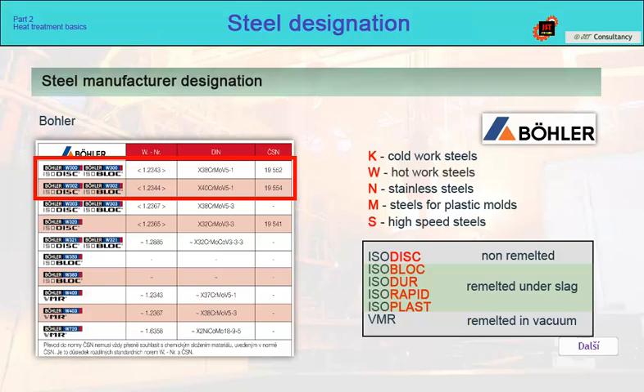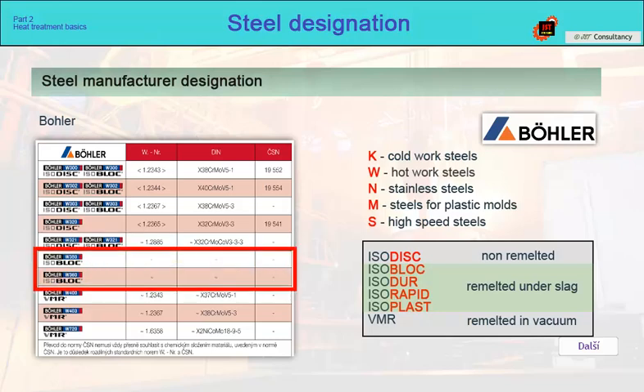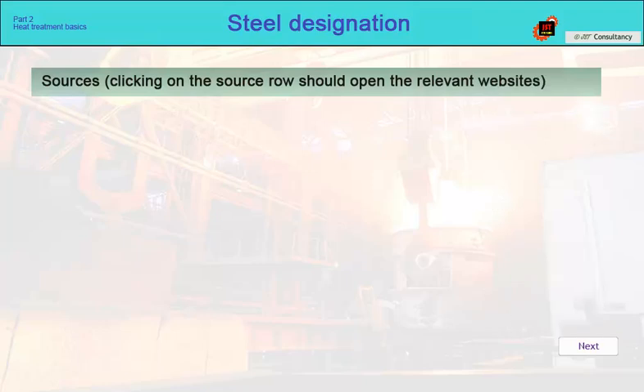For example, steels W300 or W302 have their equivalents, but heat treatment should be carried out according to the Böhler regulation. However, as can be seen from the table, some steels completely deviate from the EN designation and therefore have no equivalent. See, for example, W350 or W360 steels. As is clear from the previous information, steel designation is complicated due to the fact that there are too many designation systems.